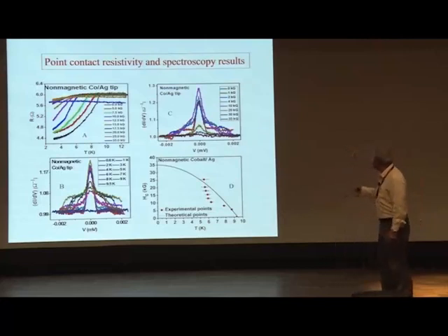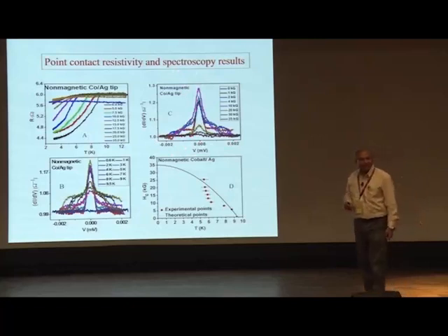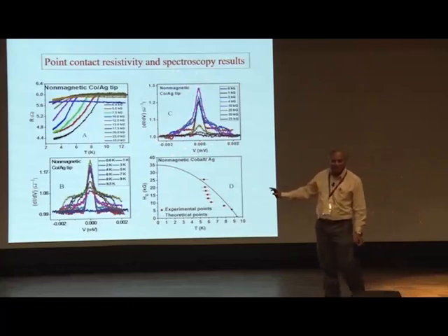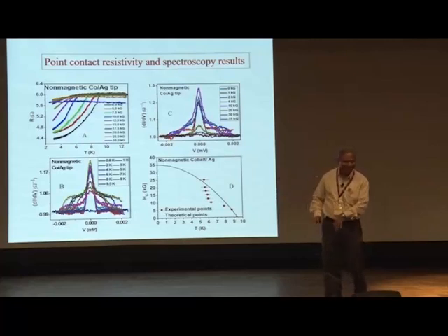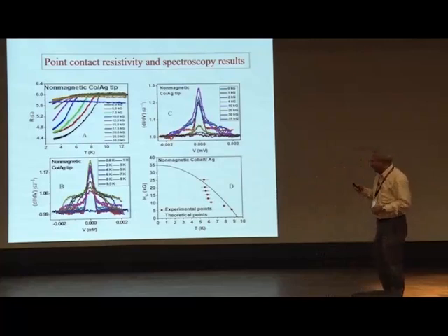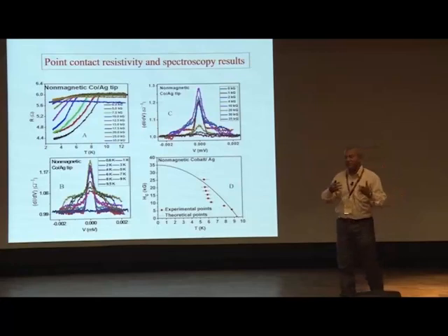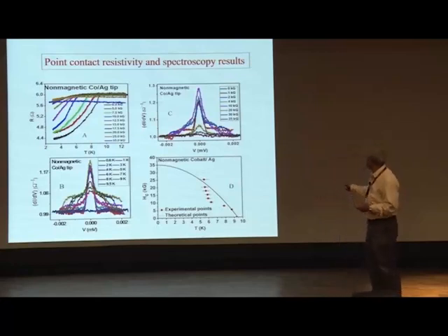And then what you have measured is the conductance as a function of applied voltage. You see that near zero voltage, there's a huge conductance peak appearing there. To explain how it appears, I have a cartoon, but I put it below the whole talk, considering the time limitation. I'll talk about it later. This is the feature that you see when you have a contact between a normal metal and a superconductor. If you apply magnetic field, the conductance peak reduces, and at about 35 kilogauss it goes flat.